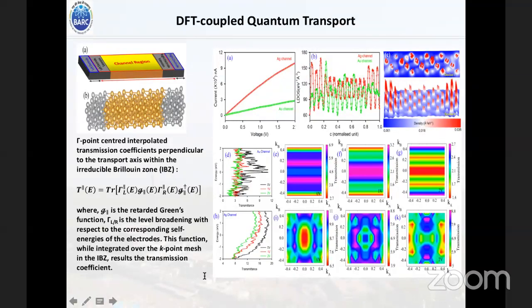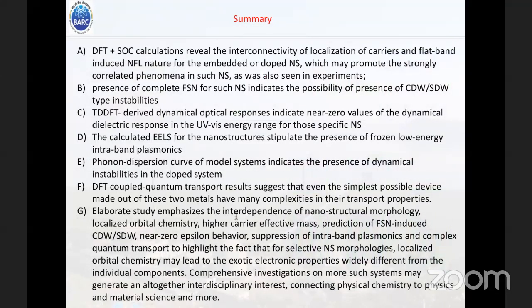So I have 2 minutes to wind up. With that, we can conclude here that for these kinds of nanostructured systems, there are interesting nanostructural morphologies. We are having localized orbital chemistry, higher carrier effective mass, prediction of FSN-induced instability, near zero epsilon behavior, suppression of intra-band plasmonics and complex quantum transport, to highlight the fact that for selective nanostructural morphologies, localized orbital chemistry may lead to exotic electronic properties which are widely different from the individual compounds. So this is of interdisciplinary interest, connecting physical chemistry to physics and material science and more. So at the end, I will thank everybody for your patience.